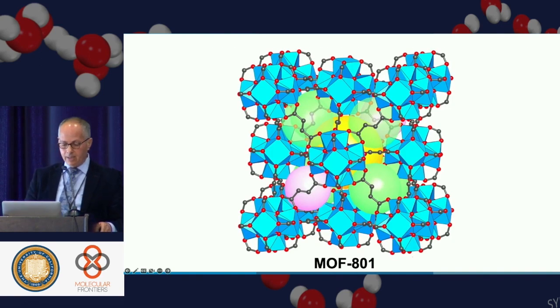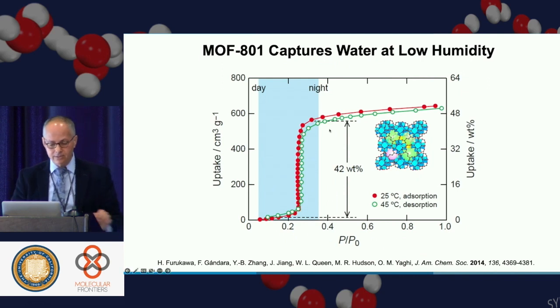So I wouldn't be telling you about this if we didn't have the MOFs in hand already, right? So we were studying CO2 capture, and CO2 capture you have separated from water. So we were studying also water harvesting, and this is the first MOF where it showed that in fact you could do this. Here's the uptake of water in that MOF. You see here that the amazing thing is that it's taking up water at around 20% relative humidity and doing so using this sharp knee behavior, which means that for me to take out this water, I only need to change the pressure by just a few digits, basically, to lower the pressure slightly to get the water out. But thermally, you can take the water out at 45 degrees.